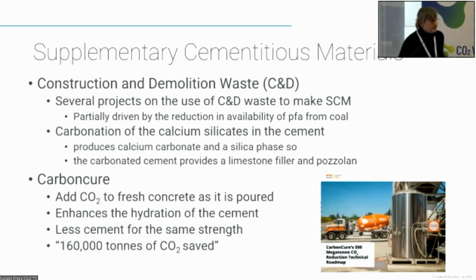Several projects have been using the C&D waste to make SCMs, partly driven by the fact that our other SCMs are diminishing. We use extensively PFA from coal-powered power stations, and also blast furnace slag have been used in cement for a long time and have important properties in the cement. But if you carbonate the calcium silicates in the cement, you can produce both a calcium carbonate and a silica phase, which provides a limestone filler and what's called a pozzolan, which helps with the cementitious properties of the overall cement.